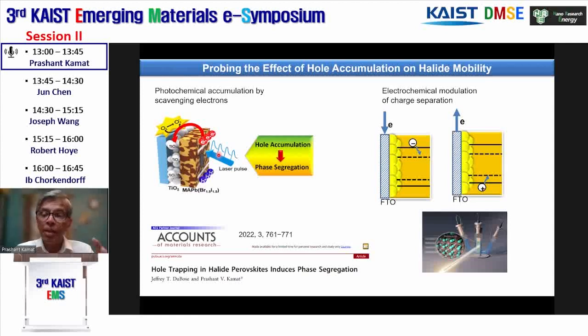In this case, what happens is, if you have a perovskite film coated on a glass slide or an insulating layer like zirconium oxide, these charge carriers that you generate are recombined. Any segregation that occurs is recovered back in the dark cycle. As a result, when you put this pulse laser, you don't see any segregation.